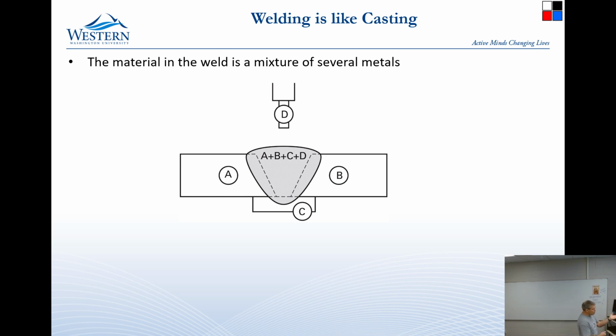So we have to choose what its properties are, and we choose its properties by choosing what material we're putting in as the filler metal. So we almost always make the filler metal have a higher strength than the base metals. Almost always. And that's called overmatched. So if we are putting in a higher strength filler metal, then that's an overmatched weld.